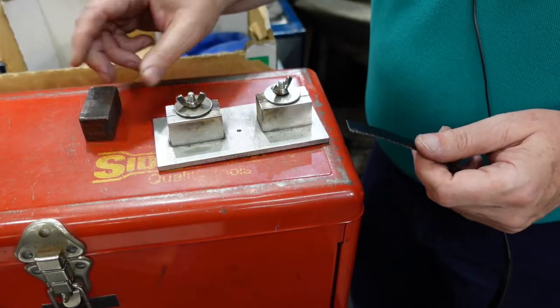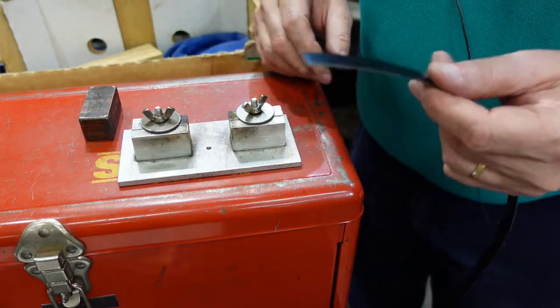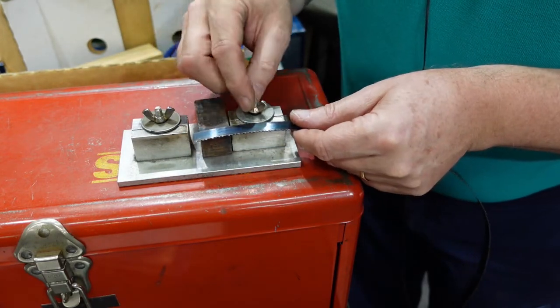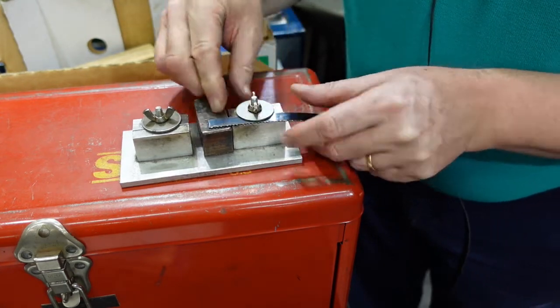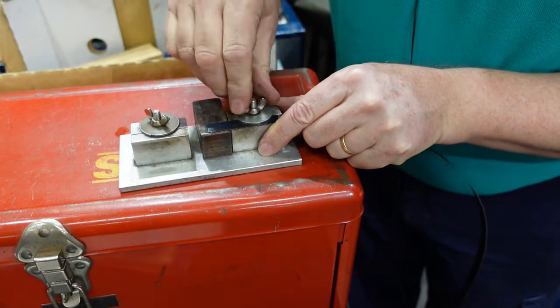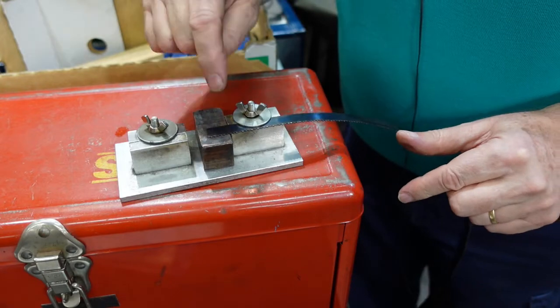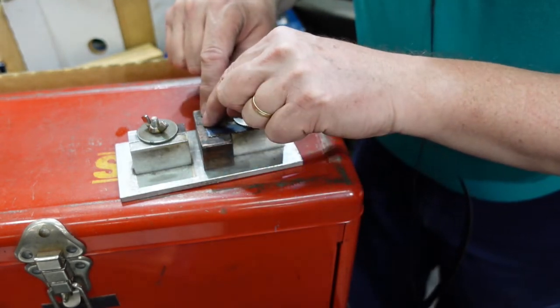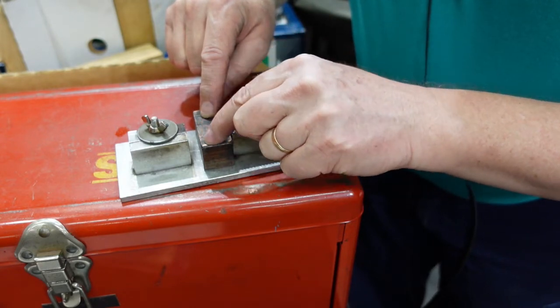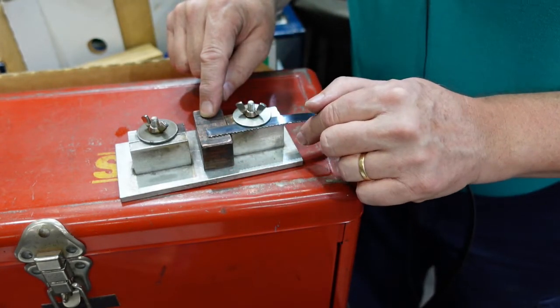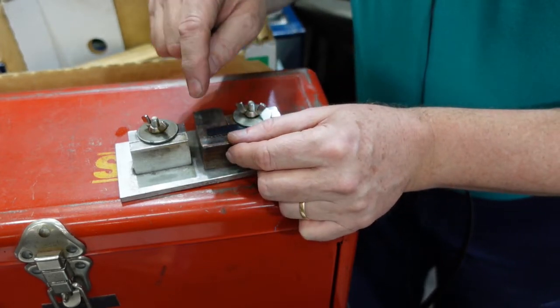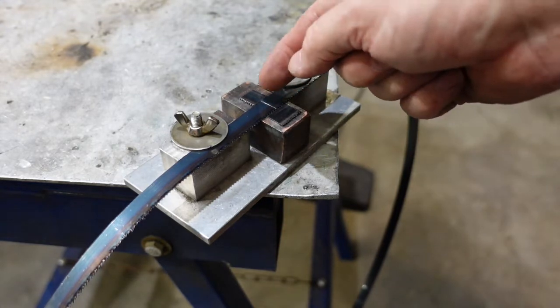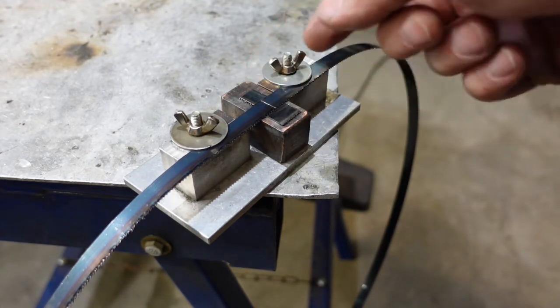This is my welding jig. It's made out of a bit of scrap aluminum, nothing terribly complicated about it, but that copper block is just the same height as that. So what I do is I use these, they're just a wing nut with an oversized washer to hold the blade. I'll do the same on the other side and then I'll put a run-on and run-off tab on either side here so that I can start my arc on the run-on tab, come across, and then finish hopefully on the run-off tab. That way I don't get any holes or pits or anything like that on the end of the blade. So there you can see the blade to be welded mounted up, I've got my tab there, tab there, I'll start the arc.